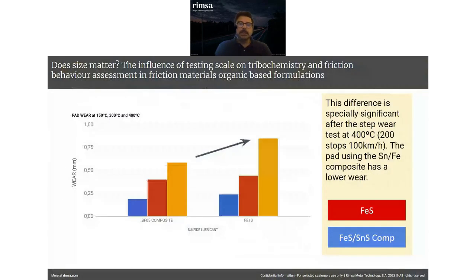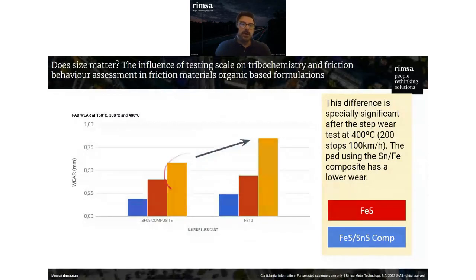The difference is, if we measure the wear of the brake pad after this test on the dynamometer, we see that at 400 degrees, this is what we see here: the wear in millimeters of the brake pad happening at 150 degrees, happening at 300 degrees, happening at 400 degrees. When we use this composite, this iron tin sulfide, we have a lower wear at high temperature compared with the pure iron sulfide. When we use this FeS, the wear is higher.